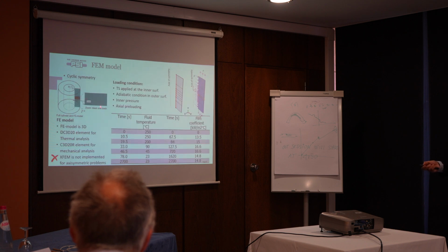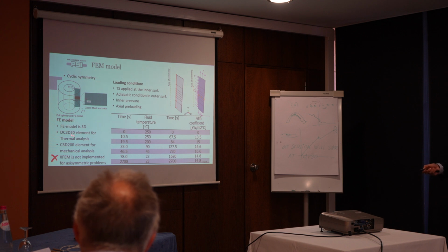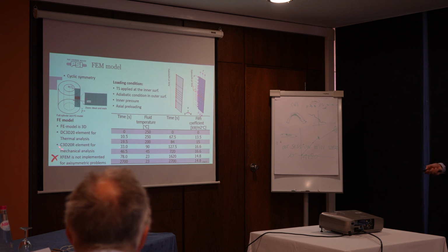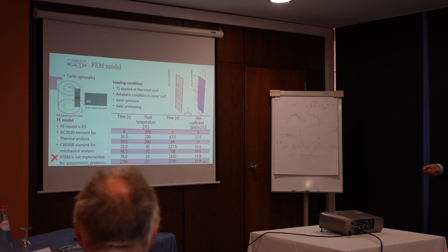This is the FEM model. As XFEM in Abaqus is restricted only to plane strain or plane stress cases and also 3D cases, we decided to use cyclic symmetry. Basically this allows us to use 3D elements, and of course we have to change the type of element depending on the simulations that we are doing. For the thermal analysis we use this type of element, and we change it for the mechanical analysis. Also we have to change it again for the fracture mechanics analysis.